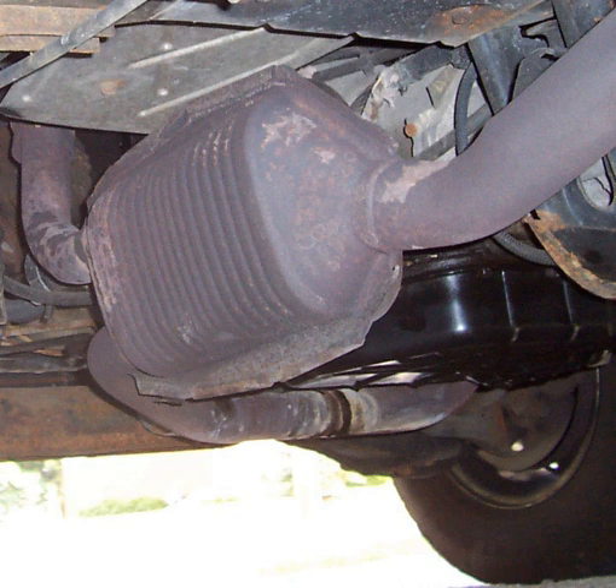Any sulfur in the fuel can be oxidized to SO2, sulfur dioxide, or even SO3, sulfur trioxide in the combustion chamber. If sulfur passes over a catalyst, it may be further oxidized in the catalyst, i.e., SO2 may be further oxidized to SO3. Sulfur oxides are precursors to sulfuric acid, a major component of acid rain. While it is possible to add substances such as vanadium to the catalyst washcoat to combat sulfur oxide formation, such addition will reduce the effectiveness of the catalyst. The most effective solution is to further refine fuel at the refinery to produce ultra-low sulfur diesel.